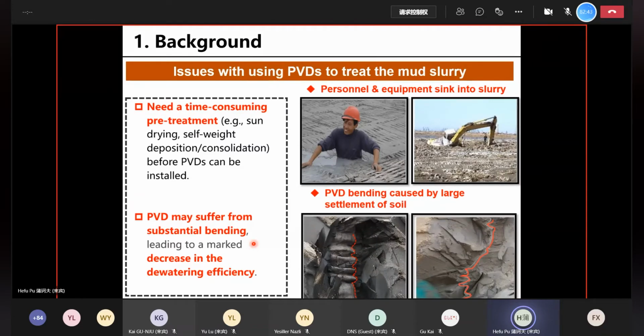The first issue is that, as I mentioned earlier, the mud slurry has very high water content. That means it has very low bearing capacity. So in the very beginning, the personnel and equipment cannot access the construction site. They may even sink into the slurry. So usually there is a very long time-consuming pre-treatment before those PVDs, those vertical drains, can be inserted into the ground. The pre-treatment includes some drying or sometimes sedimentation or consolidation, depending on the method used and depending on the scale of the construction site. The pre-treatment can be very long, sometimes months or even years.